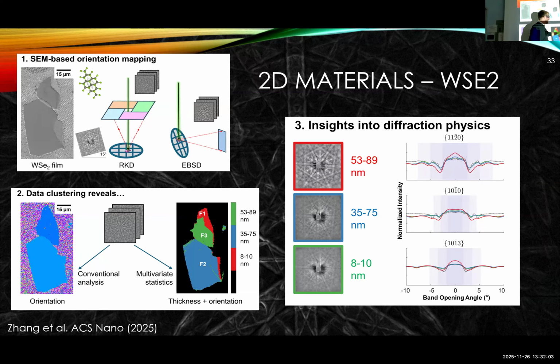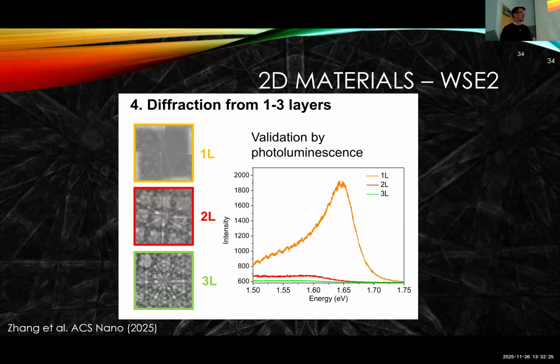And then we also got diffraction patterns from the many layer problem, so 8 to 10 nanometers up to 90 nanometers. We see microstructure across this flake. There's different regions, there's a grain boundary and a few other bits and pieces. And we use some posh statistics or machine learning to help us decompose the characteristic signals for this case. We can also get it from single layer, 2 layer, and 3 layer. And because people don't trust diffraction people to get 1 or 2 or 3 layers, we can verify that with photoluminescence to check the layer thickness, because tungsten diselenide has different PL effects with thickness in this case.